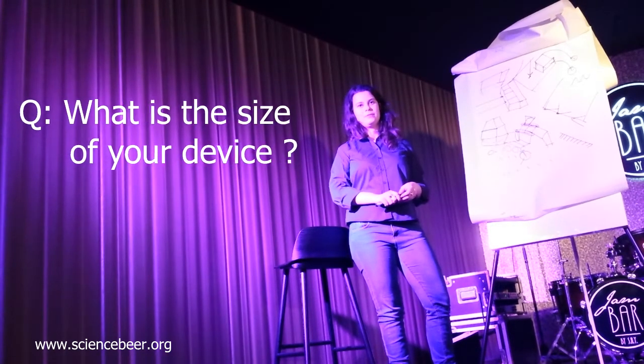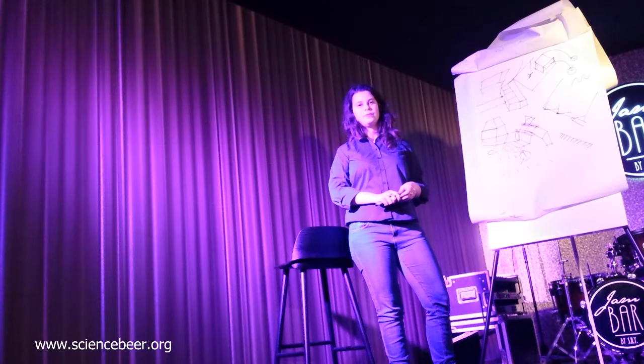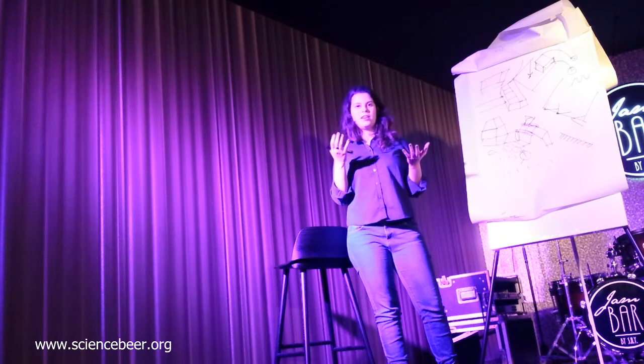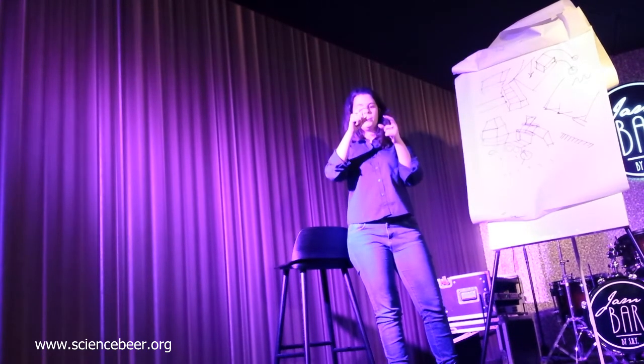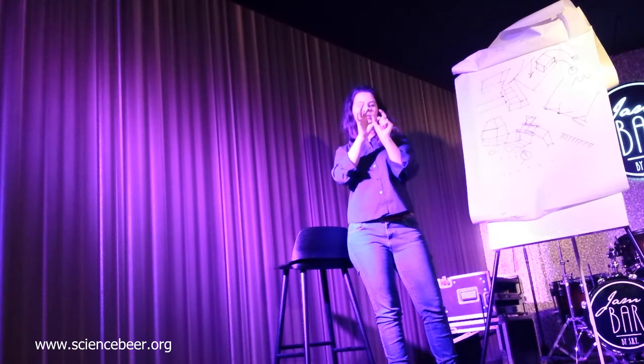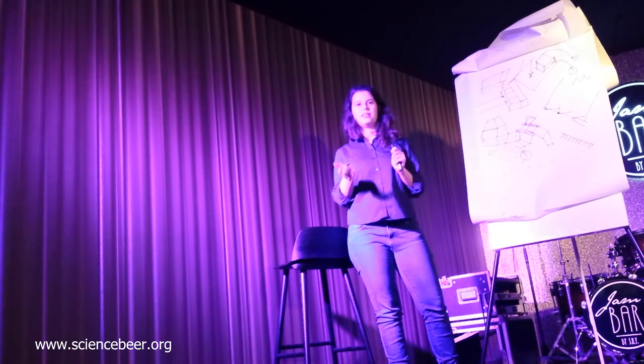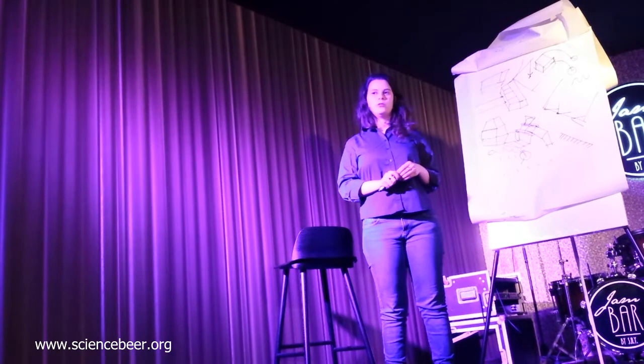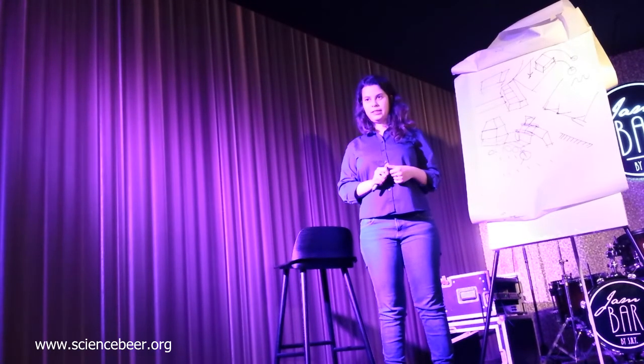What is the size that you are handling there, of your device and the printing? One single device has 100 micrometer channels, but the whole sample depends on how big you would like to make your blade and your substrate. At the moment, we can make samples up to 4 centimeters by 2, so 8 square centimeters, in a few seconds. But what's the thickness of your layer? The very good ones are around 15 to 20 nanometers. The thinnest that I have made were 7 nanometers.